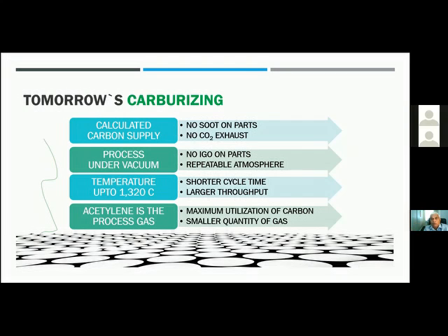Secondly, you get absolutely no CO2 coming out of the exhaust. In fact, the only exhaust you get is water vapor. The process is typically done under vacuum. Now, the definition of vacuum is 1000 millibar absolute or 760 torr absolute. Anything below 760 torr or 1000 millibar would technically be vacuum. So carburizing is always done in partial pressure, which is vacuum, which means there is no oxygen.